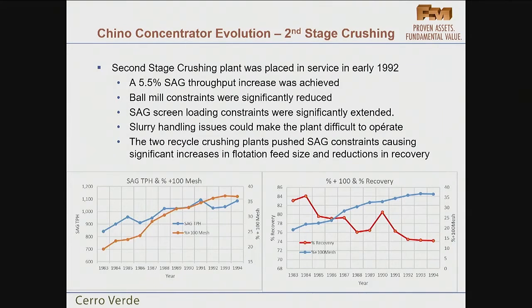You see in the graphs below, the blue one on the left side is SAG throughput from '83 to the '94-ish area. Continuous improvement. The red or the orange is the percent plus 100 mesh. So we're driving throughput up, driving flotation feed size up. Plot on the right is, again, the blue is percent plus 100 mesh, a continuous increase from approximately 20% plus 100 mesh to 37%. Where the red is the recovery, dropping from 83, 84-ish down to 74. I guess there's a relationship.